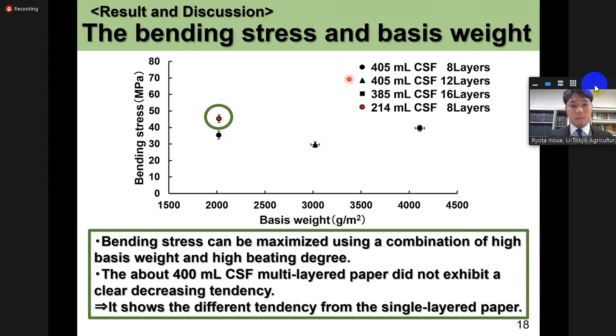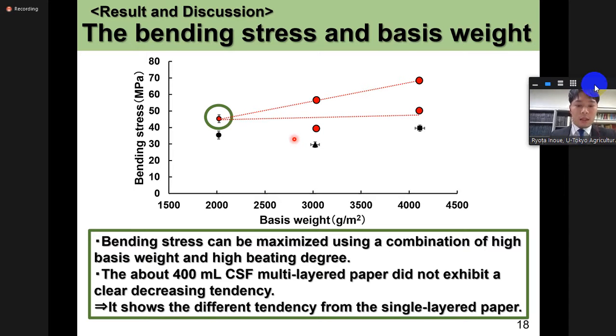This figure shows the relationship between the bending stress and the base weight of multi-layered paper. The red point indicates high beating degree. This point shows that bending stress can be maximized using a combination of high base weight and high beating degree. The about 400 milliliters CSF multi-layered paper did not exhibit a clear decreasing tendency. You can notice that it shows a different tendency from the single-layered paper. It can be expected that the red point in the further high base weight region also will not show a clear decreasing tendency or will show a positive correlation.